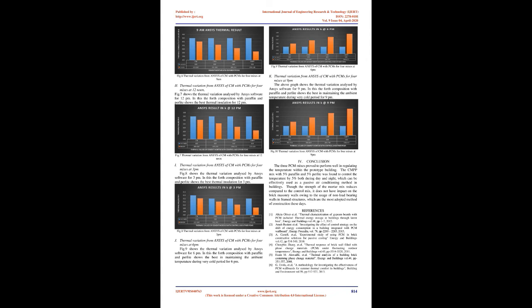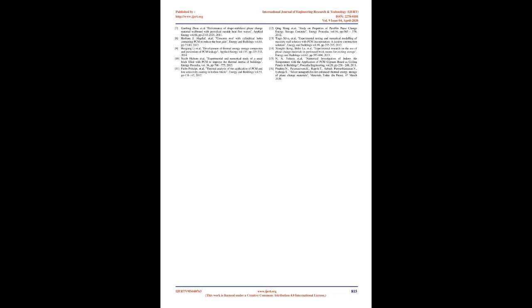D. Temperature variation of outside, CM and CMG mixes. The variation of temperatures is shown in a graph for respective 12 hours timely readings. Fig.3 shows the average temperature between outside temperature and CM without PCM and CMG. The CMG was found to give better results with reduction in temperature of 3% during daytime and increase in temperature of 3% during nighttime. Fig.3 Temperature variation of outside, CM and CMG mixes.